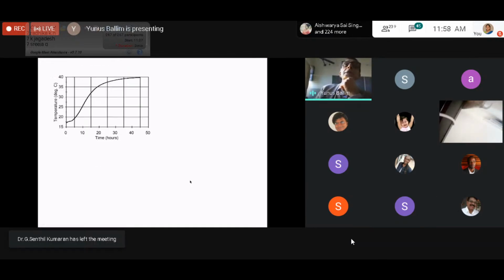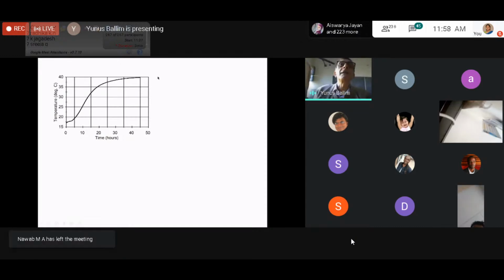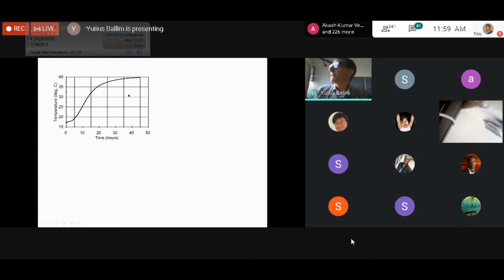Using that piece of equipment, it's possible to develop a curve like this, where you plot temperature versus time, and you can get very good results. And as you can see from this, it actually continues. Hydration is continuing after we've got 45 hours. Hydration is continuing, but as I said, we lose sensitivity with that instrument, and so the instrument tends to lose its ability to measure small changes in heat evolution.